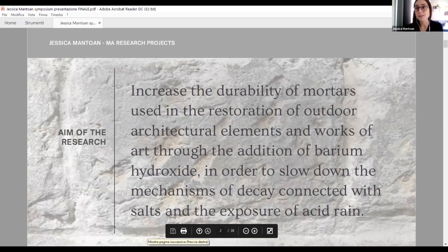And my idea was that through the use of barium hydroxide, I would be able to increase the durability of mortar, slowing down the mechanism of decay related to the nucleation of soluble salt, in particular sulfate salt, and the decay connected to acid rain.